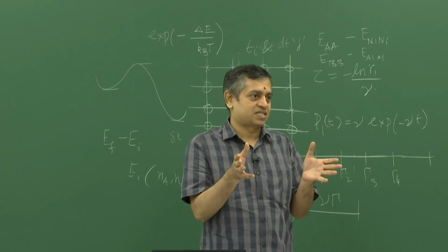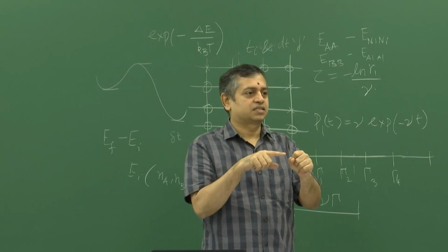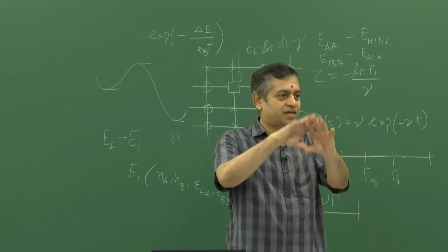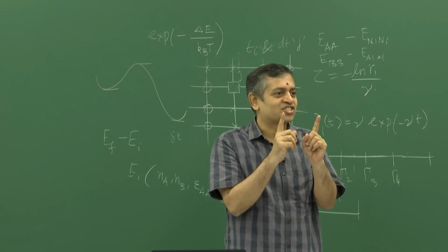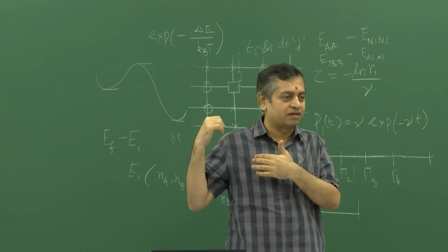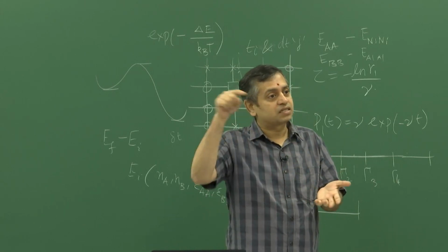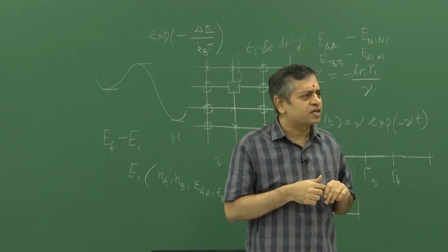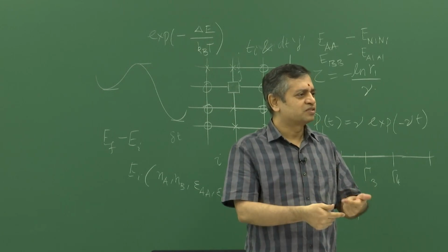Only if you have a binary system and you have some B atoms sitting, then you can look at B atom clusters. Even there, if you look at A atom clusters, like what Ferdi had, blue in which some orange atoms were forming the precipitates, it will still say only one cluster for the blue, because that is a single cluster, and I will show the algorithm in the afternoon. So you will see why it is one cluster. Only for the precipitates will it start labeling them as different. But I am assuming that it is Hoshen-Kopelman, because all of them are finally just union and find. It is only the way you do it.